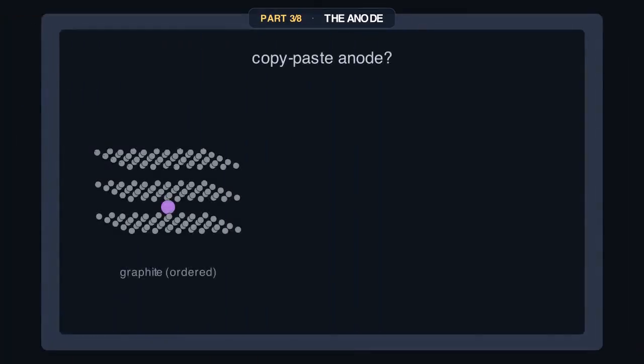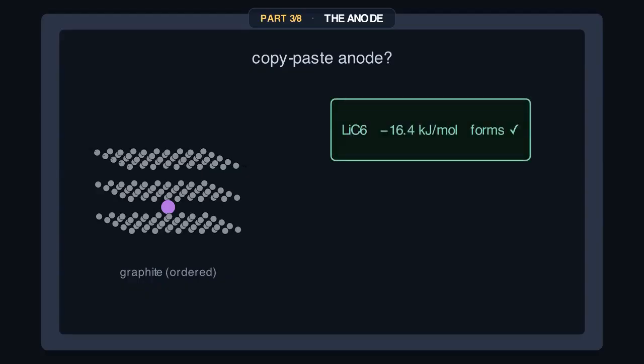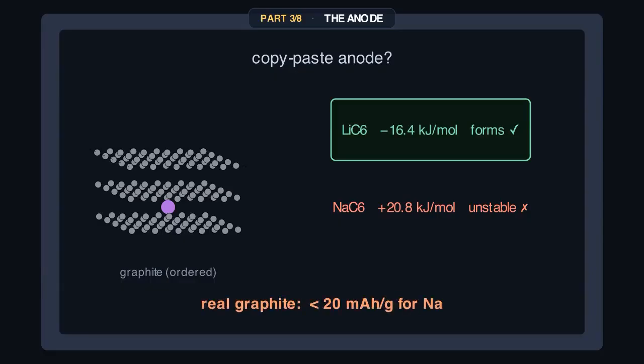Watch this break. For lithium, packing 1 lithium per 6 carbons releases energy, minus 16.4 kilojoules per mole. It's stable, it wants to form. For sodium, the very same structure costs energy, plus 20.8 kilojoules per mole. Positive, it does not want to exist. In real graphite, sodium manages barely 20 milliamp-hours per gram, basically useless. Our copy-paste anode just failed on the board.